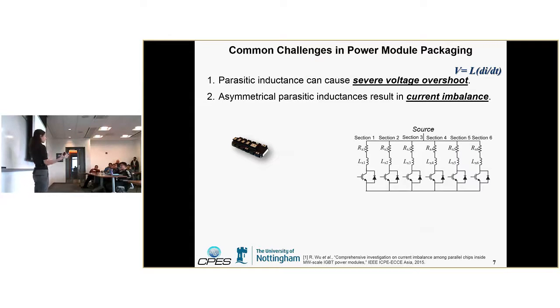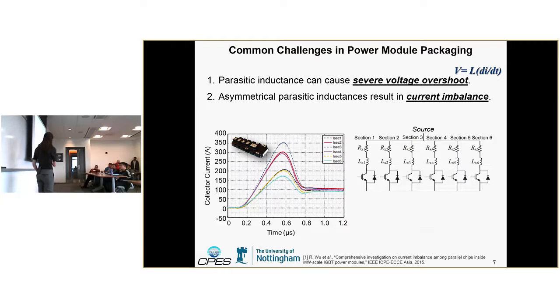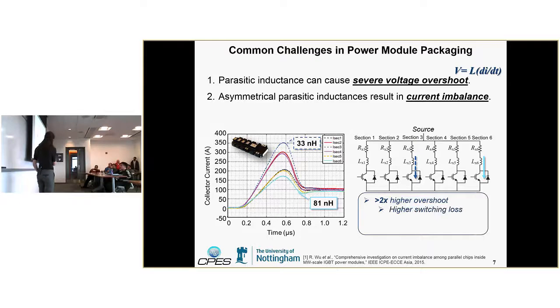In order to increase the current of your power module, you need to put multiple semiconductor die in parallel. Here's an example for a silicon IGBT. There are 6 die in parallel, 6 IGBTs in parallel, and this is the terminal to the rest of your system. This is a look at the turn on transient, and this is your current here. You can see that die number 6 is the farthest from the source terminal, so it has the highest parasitic inductance, and hence during the transient, it has the lowest current overshoot. Whereas die number 3 is the closest, and so it has more than 2 times higher current overshoot during the turn on transient. This is significant because it means the switching losses are not symmetrical for all the die, so the heating is also going to be different.